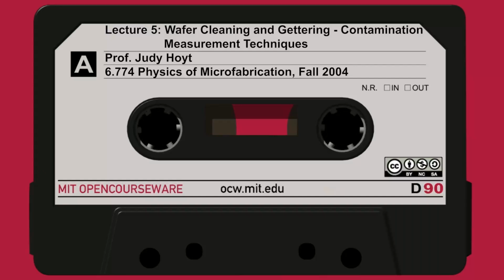And finally, going back to slide 12, it has a relatively small detection area. Say 50 by 50 microns, still not that small compared to the size of a device, but it's better than 10 millimeters. So you can put special structures on the mask with this kind of size area that are dedicated for device characterization. If you're doing research and you want to be able to measure on the chip, measure the characterization, the contamination.